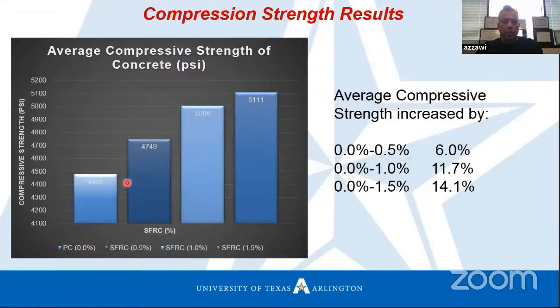We see the increase in compressive strength. Yes, it is not a big increase between 1% and 1.5%. That is expected because as we put in more fibers, the compressive strength will not increase further.